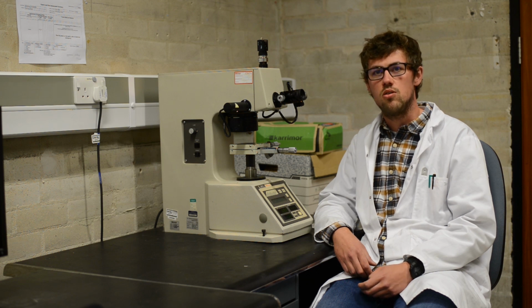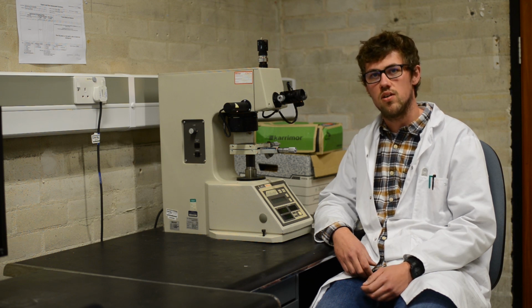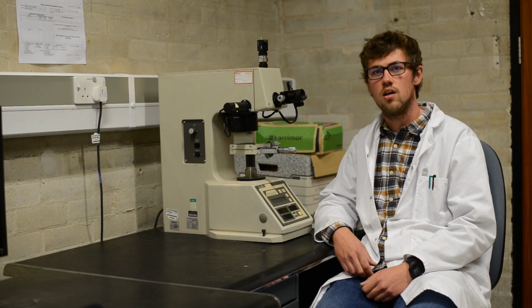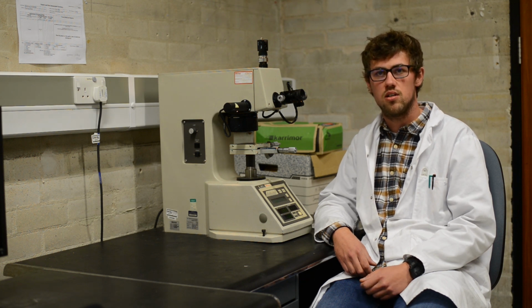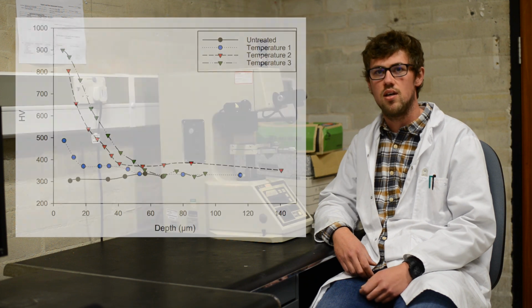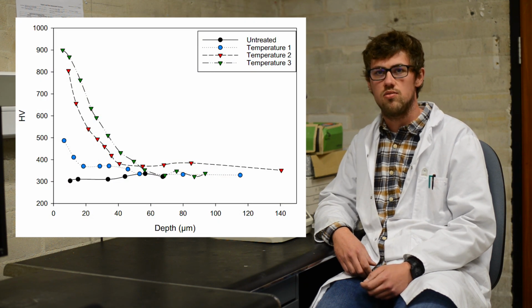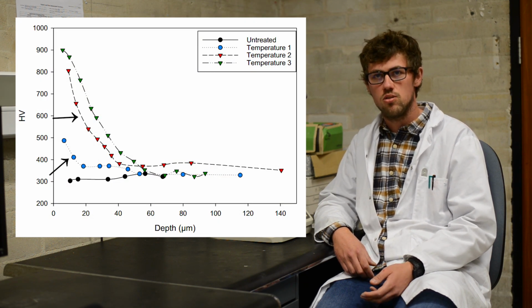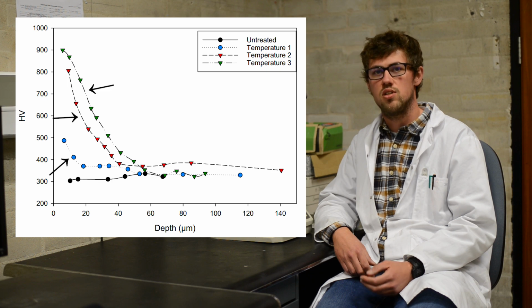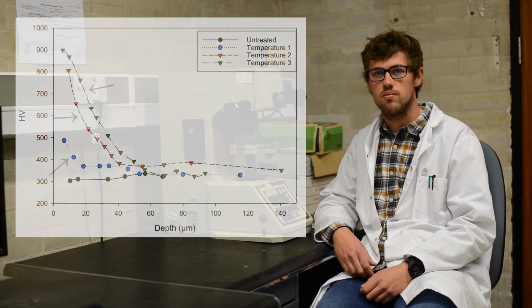Not only can you measure the surface hardness of a sample, but if you create a cross-section of your sample, you can also measure the variance in hardness value along this cross-section, where with diffusion-based treatments, you will see a gradual reduction in hardness value with increasing depth, as shown here, where increasing from temperature 1 to 2 to 3 resulted in increasing diffusion depth.